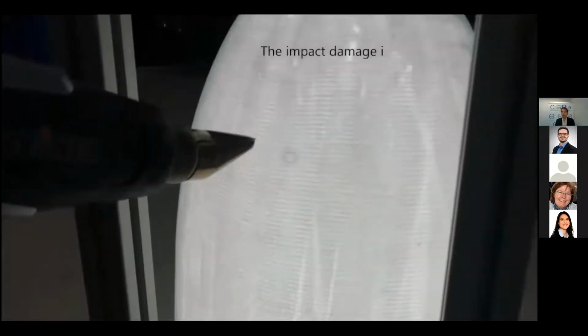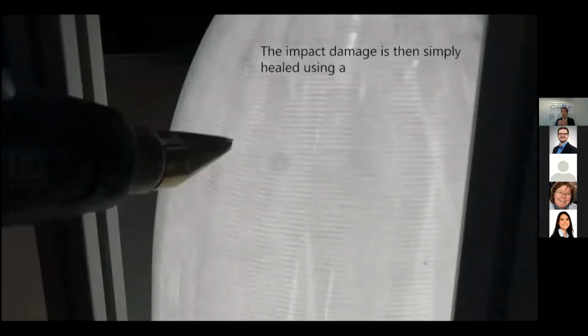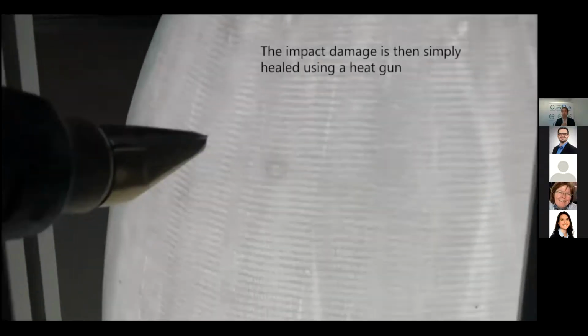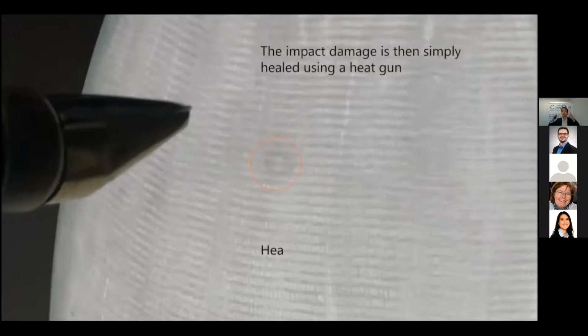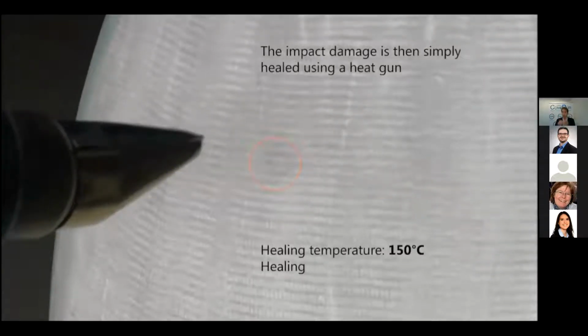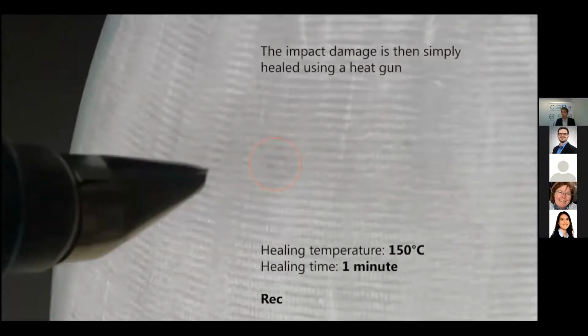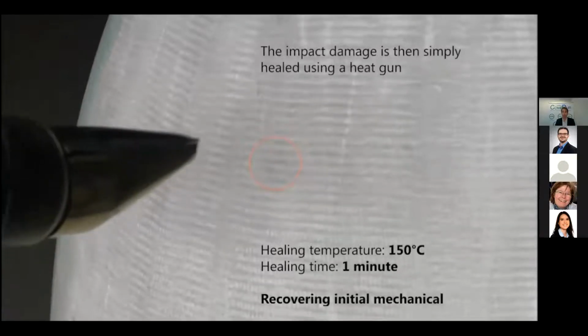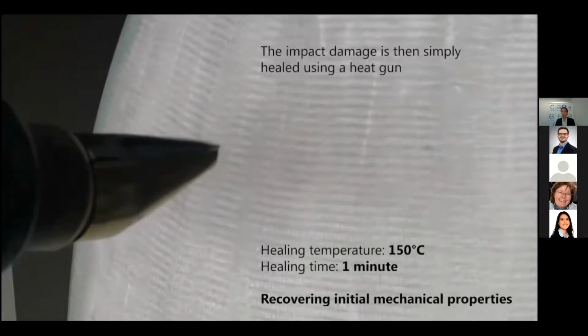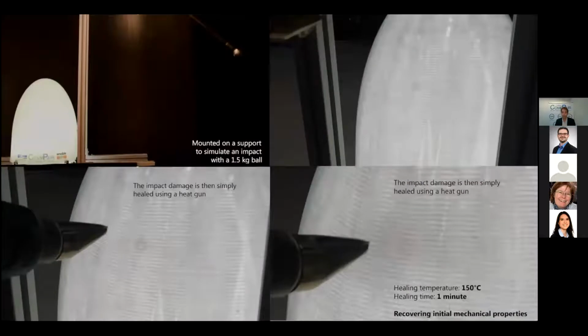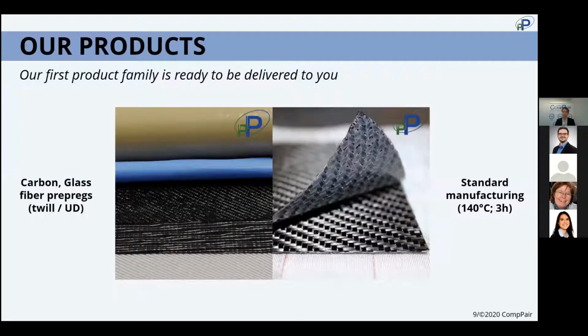To demonstrate such technology, what we have done is to run several demonstrations, but specifically that one, which is typical of the aerospace industry. We impacted it, and here you are able to see a typical damage. So for you, this might be critical, and we know that this is critical because it will just grow into a larger damage. And you will spend normally several hours to repair it. With our solution, this is simple, 150 degrees for 1 minute, and it's done. You recover fully the mechanical properties.